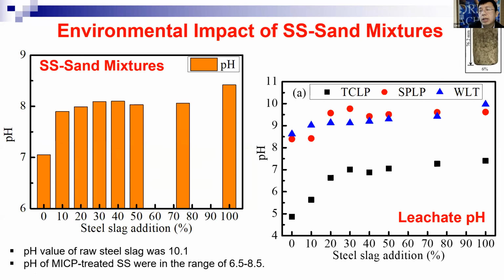When they reach about 30%, they start to leach off. So that's the final pH for the TCLP, which reached 7. But remember, for the TCLP we put in an extraction fluid of 2.88. So originally you put in 2.88, but after leaching testing, you reach about 7.